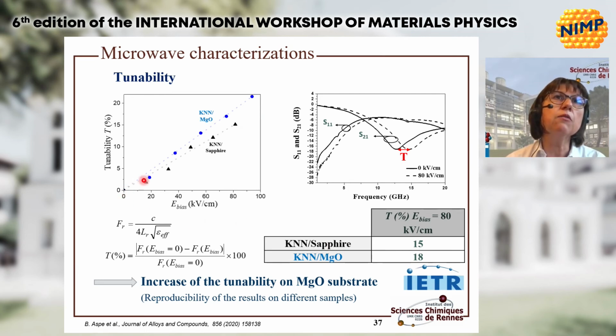You can see here the evolution of the tunability, which increases above 20% for 100 kilovolts per centimeter as bias. In comparison with sapphire, it has not been possible to increase the voltage more on the sapphire substrate. This increase of the tunability on MgO substrate has been measured with reproducibility on different samples, so it's systematic.